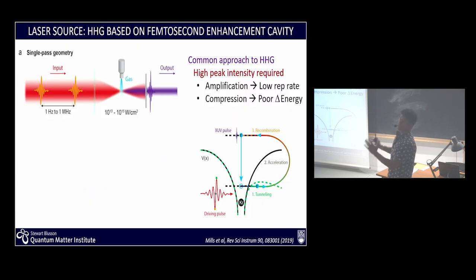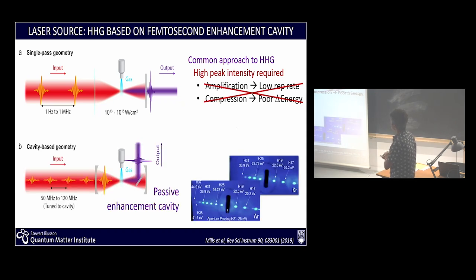Just one slide about the laser. So usually we want to go to high photon energy. We use a gas jet, and the challenge is you need very strongly amplified pulses, so that means low repetition rates. You also have to have very short pulses, so compression, which immediately also means low energy resolution. And so we wanted to get beyond that to really get the best of the two, so high energy and temporal resolutions. So the idea was to put a cavity around the gas jet, and now we have a repetition rate which is defined by the period around this cavity. So in fact, we work at 60 megahertz.